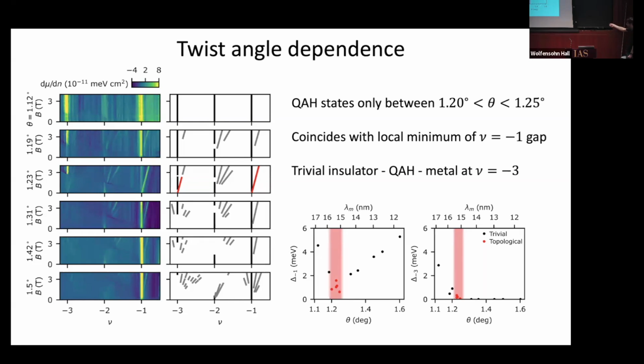And similarly, you can plot the same thing for nu equals negative 3. In this same window of twist angles, you get topology of that state. And then at lower twist angles, you can see that it's, again, a trivial state. At higher twist angles, we don't even see an incompressible state at nu equals negative 3. Presumably, the bandwidth is too large.